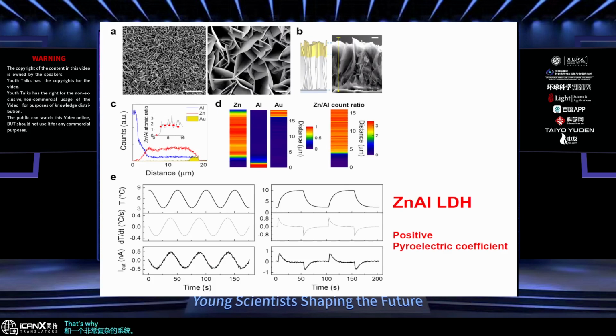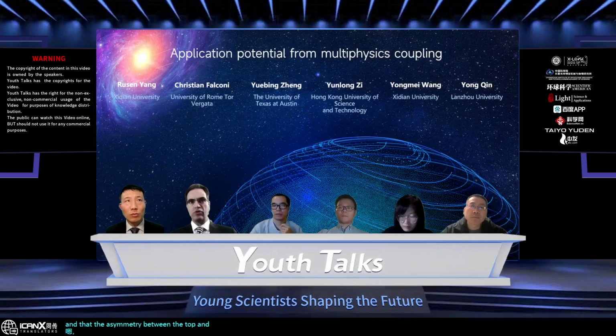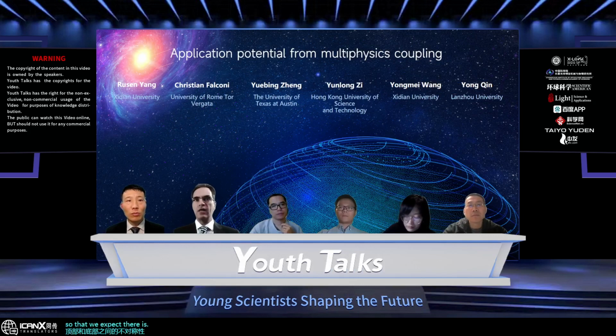So that's why in this paper we did not propose a model for the pyroelectric nanogenerators that is a clear indication, but we just restrict to giving the main reasons why we can expect the pyroelectric behavior and also that it is widely tunable. So these reasons include the size effects, the composition gradient that has been shown previously in literature to give rise to a strong pyroelectric effect, and the asymmetry between the top and bottom, so that we expect there is some polarization that, of course, will be temperature dependent.